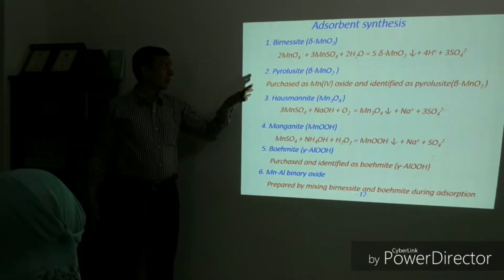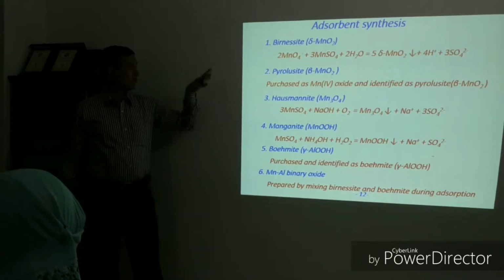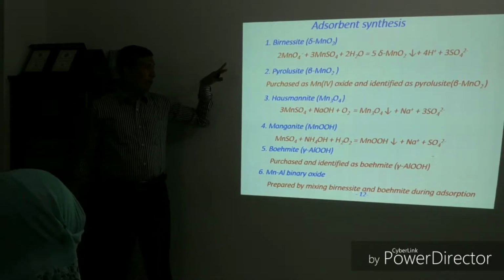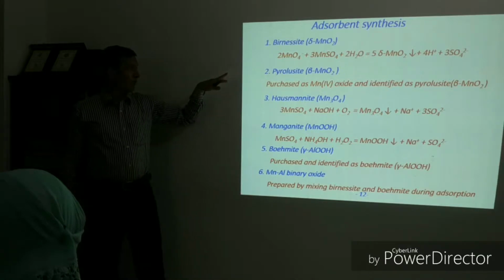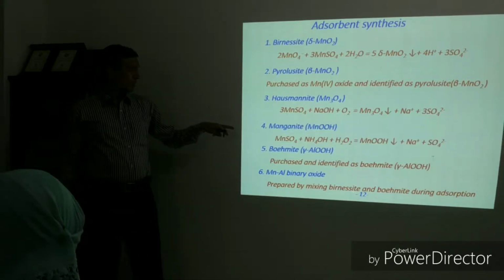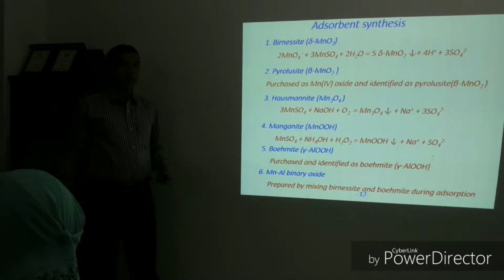Then we have synthesized adsorbents. Typically, we have used 6 different adsorbents to remove heavy metal ions and humic acid. The first one is birnessite, which was synthesized using a system containing potassium permanganate and manganese sulfate at room temperature. The second one was pyrolusite, which was purchased. The third one was synthesized using manganese sulfate and sodium hydroxide. The fourth one was synthesized using manganese sulfate and ammonium hydroxide in the presence of hydrogen peroxide.